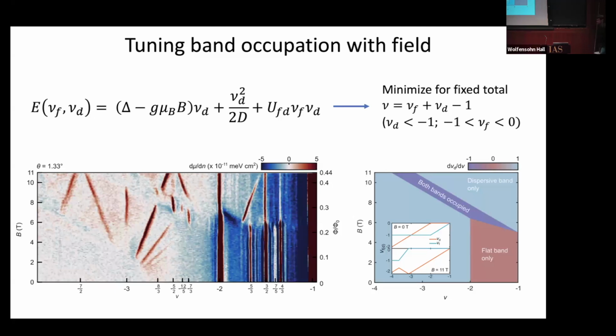Okay, so that's a good question and possibly a charged question. So it depends on your definition of Mott insulator. A lot of people in the field call these states Mott insulators. I think some people, including at my institution, will say a Mott insulator necessarily has to not have any symmetry breaking all the way down to the zero temperature limit. And if you ascribe to that point of view, I don't think that it's quite fair to call this a Mott insulator. So you would expect, as a triangular lattice, to eventually get some antiferromagnetic ordering. So in that sense, it wouldn't be.